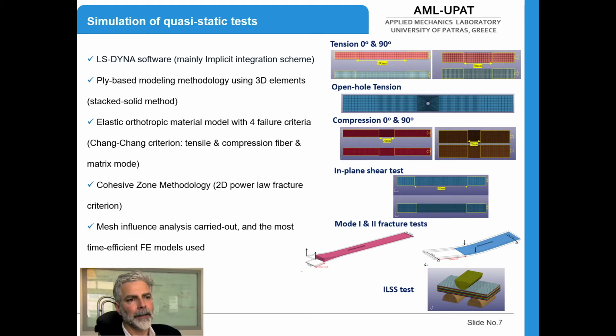The model used 3D elements, the stack solid method. By using solid elements instead of thin or thick shells, no geometric or loading assumptions are required, and the boundary conditions are treated more realistically. The solid elements allow the 3D behavior of simulated components to be fully captured. The material model considered is an elastic orthotropic material model with 4 failure criteria, and the failure criteria considered are the Chang-Chang failure criteria for tensile and compression failure of both fiber and matrix material.